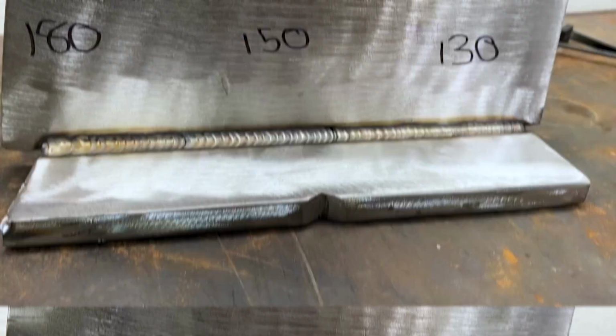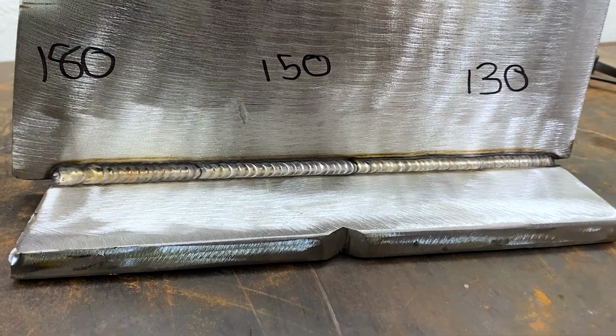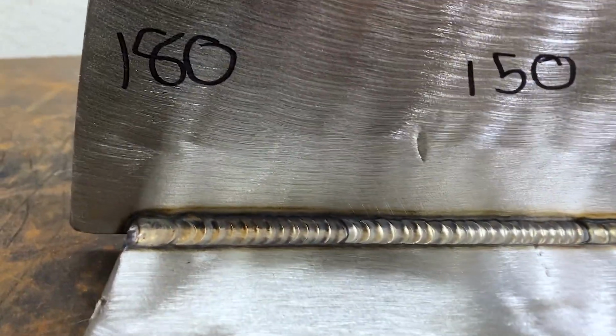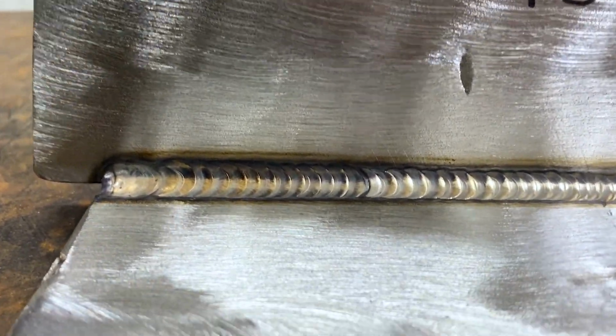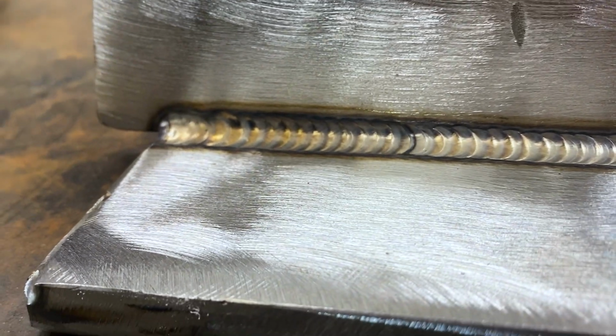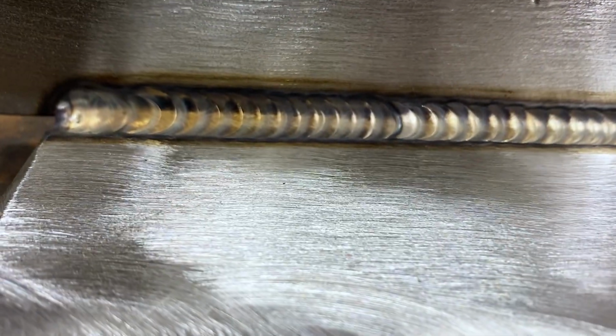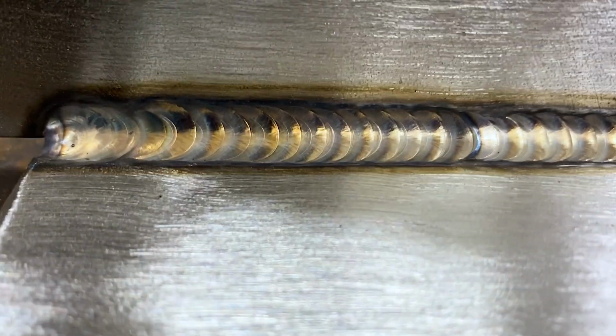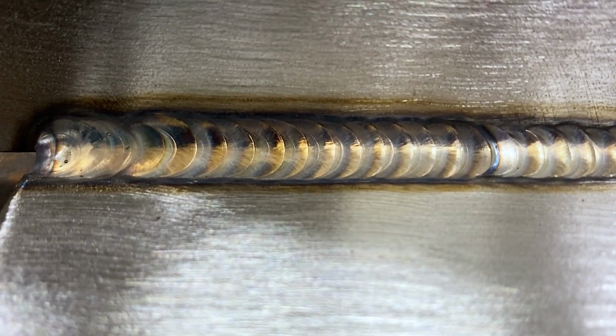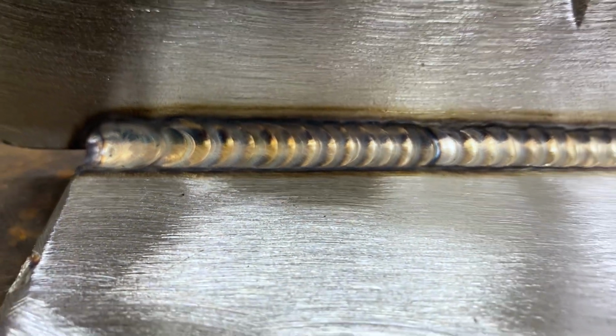I'm having to really feed the wire in and I'm chasing my puddle. So it's trying to run away from me and I'm really having to work to keep it consistent and steady. It's too hot. You'll notice here as we look at the differences between the 3 amperage ranges, how the weld gets bigger, right? So at 180, I'm having to step further apart. I'm getting slight undercut on the top end and I'm having to feed more wire. And the heat affected zone is growing.